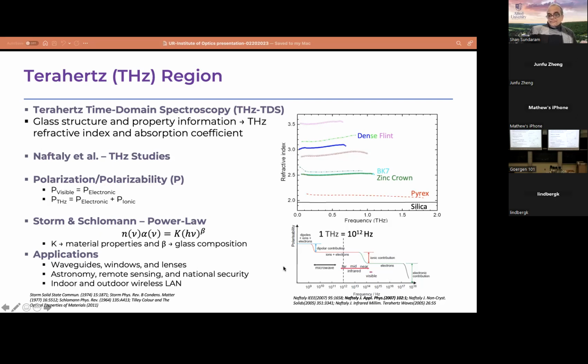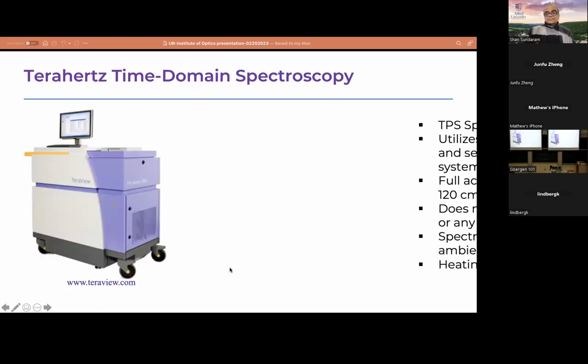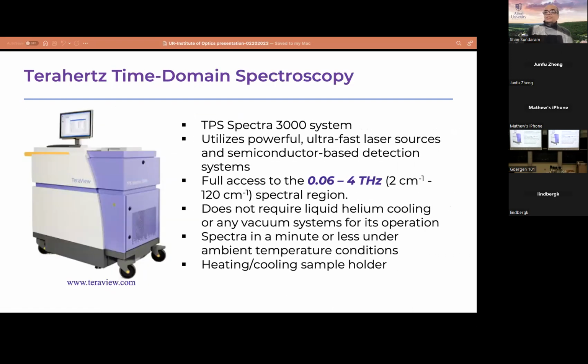I've shown you various polarization mechanisms, and you can see where the terahertz frequency lies. The spectroscopy we have at Alfred is the TPS Spectra 3000 system. It's packaged by TeraView and marketed by them. It has access to about the 0.06 to 4 terahertz spectral region. It doesn't need any liquid helium cooling or a vacuum system. It's fully packaged. We can collect spectra in a few minutes at ambient temperature. We could also heat or cool the sample holder to measure properties as a function of temperature.